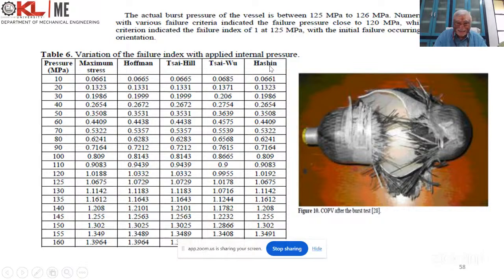When you look into it, whenever the index crosses 1, it fails. So around 110, this one is crossing; at 120, this one is crossing. The actual burst pressure is 125 to 126 megapascal, but the numerical simulation is very close to 120 with the Tsai and Wu criteria. The Tsai and Wu criteria is tallying close to that, and whatever they predicted is close to that.